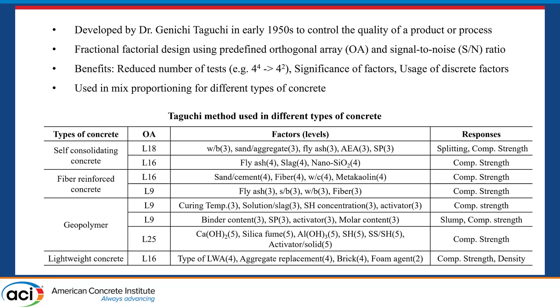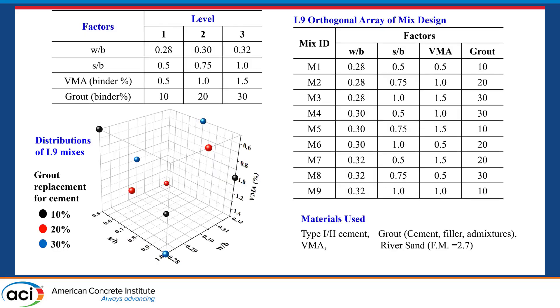In this study, we set four different factors including water-to-binder ratio, sand-to-binder ratio, dosage of VMA, and replacement ratio of grout. Each factor has three different levels. Using statistical software, we chose the L9 orthogonal array and developed nine mixes with different combinations of factors. This figure shows the combination of factors in a three-axis coordinate system, and all factors are well distributed.